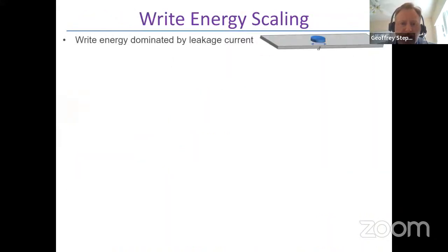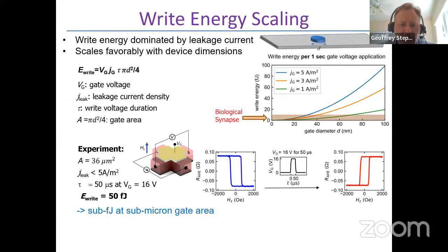And in terms of power consumption, let me step through all of the animations. As opposed to an electric current, because of the very small leakage currents in these devices and the very small scale at which they can be made, the write energy to create a skyrmion is exceptionally small. Experimentally, on tens of micron area devices, we've demonstrated 50 femtojoule writing. And that writing energy scales simply as the area for these structures. So by making reasonably small gated areas, we expect to be able to write skyrmions or write domain walls, or gate and control them in a racetrack, at energies that are comparable to or below those of a biological synapse.